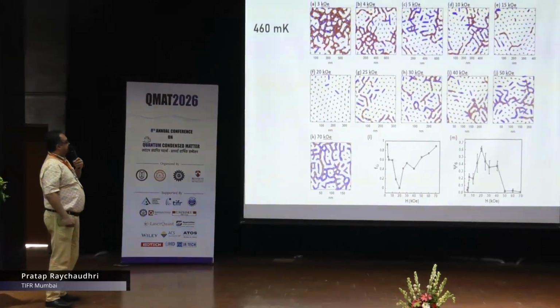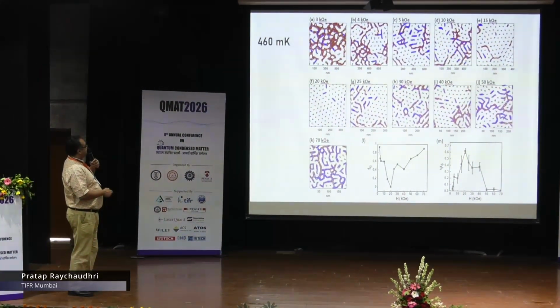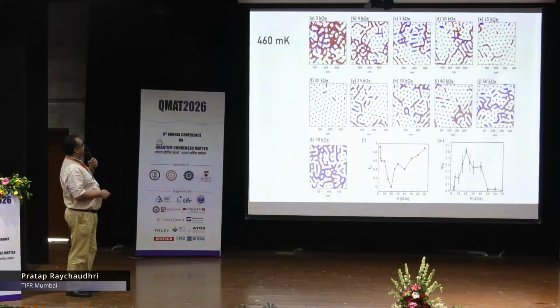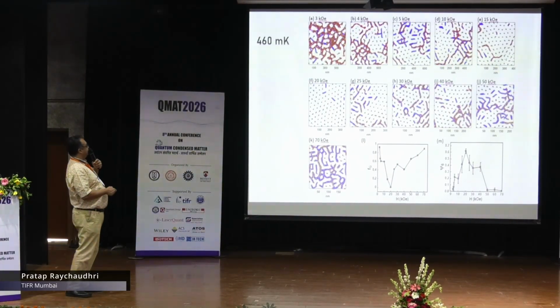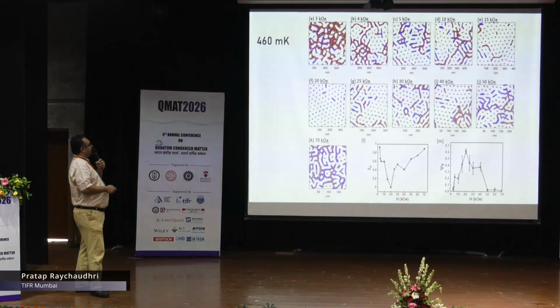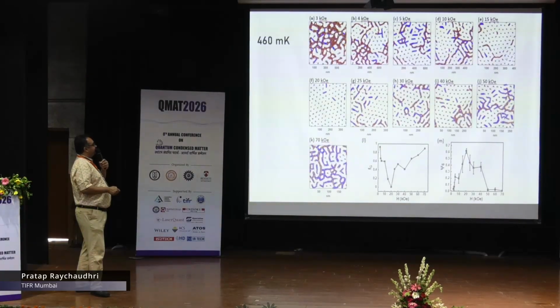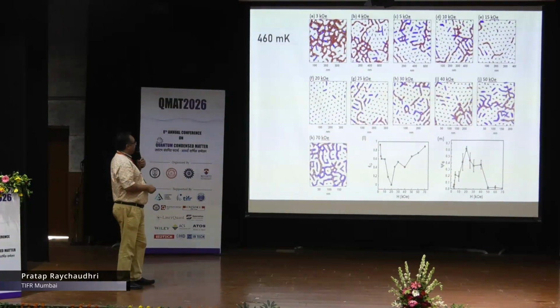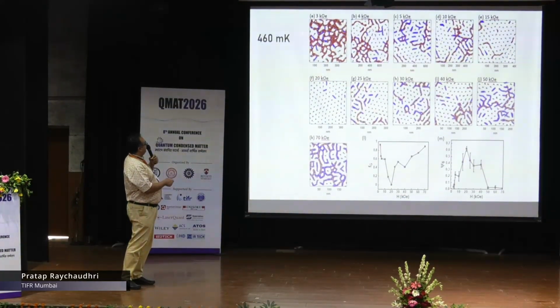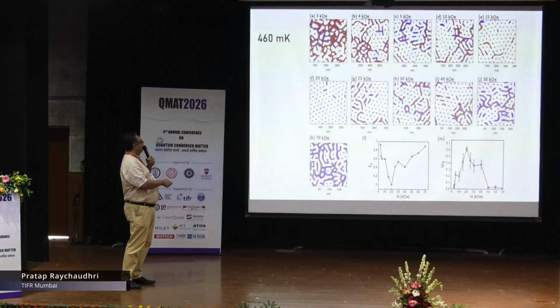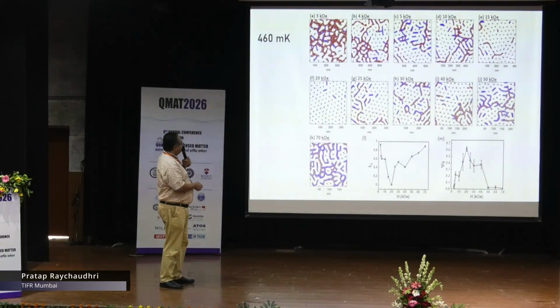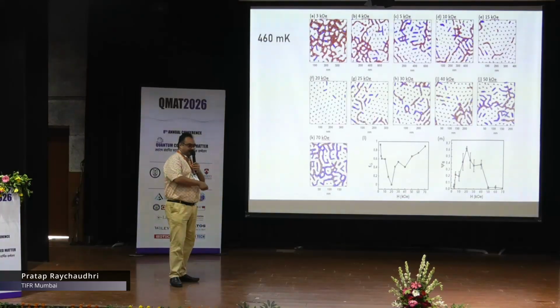Okay, what happens here? 460 millikelvin, I start at 3 kOe, I have an inhomogeneous vortex liquid. I increase field. By the time I come to 20 kOe, you see from something that was completely an inhomogeneous liquid and disordered, I have converted it into an ordered solid. Then if I increase field further, it disorders and I get eventually again an inhomogeneous vortex liquid.